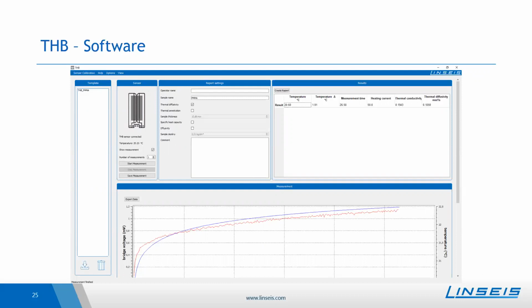There's a question regarding the specific heat capacity measurement. So some of our competitors seem to have a special cell for specific heat capacity independent measurements. This we do not offer. We offer more or less only the determination of specific heat capacity within one run, at the same time with the thermal conductivity and thermal diffusivity. Here you can see that one can select the properties which should be determined. So one can have a look onto the thermal diffusivity. So the thermal conductivity is always determined.